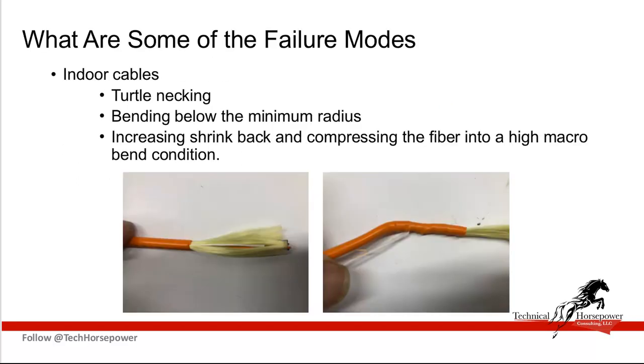Now let's talk about indoor cables, some of the failure modes. And there are terms here that probably some of you may recognize, some of you may not. I refer to one of these as turtlenecking. If you think of a turtleneck shirt, how it bundles back, or a turtle's neck, how it folds and the skin sort of collapses. If you have a simplex or even a 12-fiber cable with a fairly thin jacket, and you were to use one of the yarns as a ripcord, as you'll see in the picture on the right here, this is the same cable before being pulled. This is the cable where you've grabbed the strength member, in this case a yarn, and you've grabbed the remaining yarns and the buffered fiber and pulled.